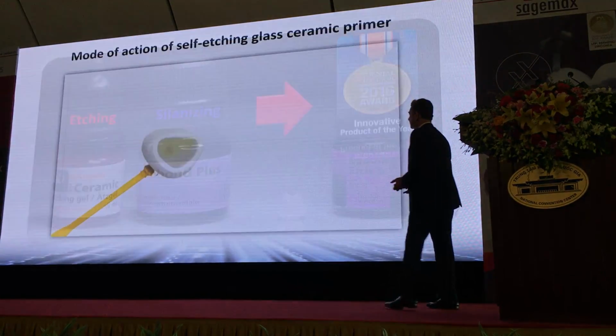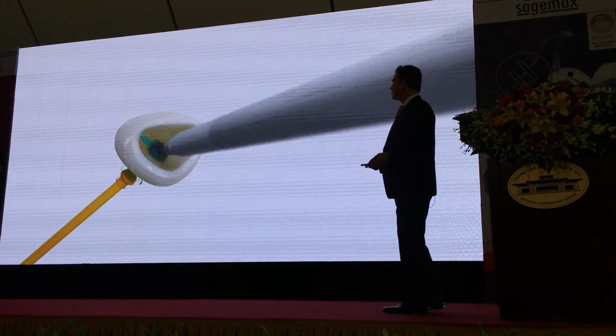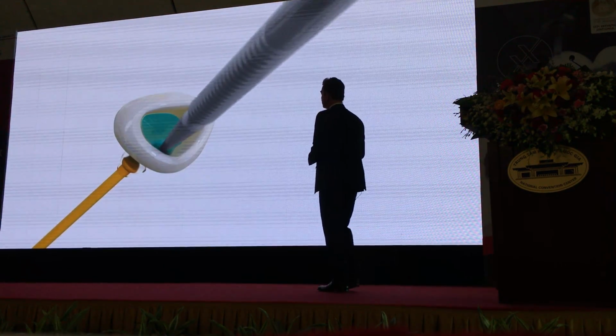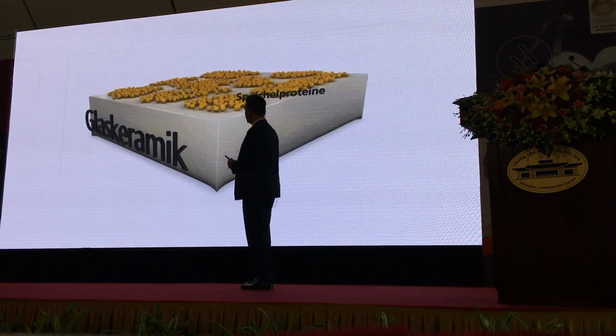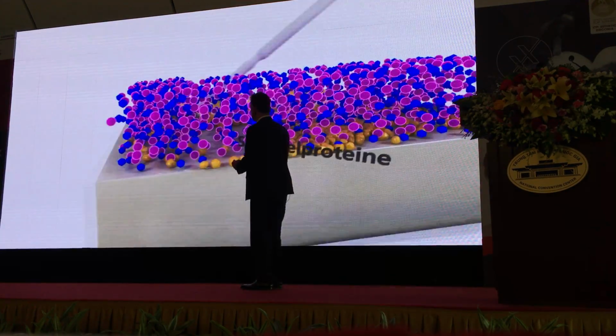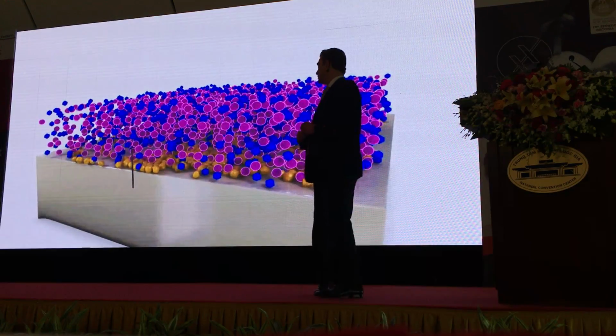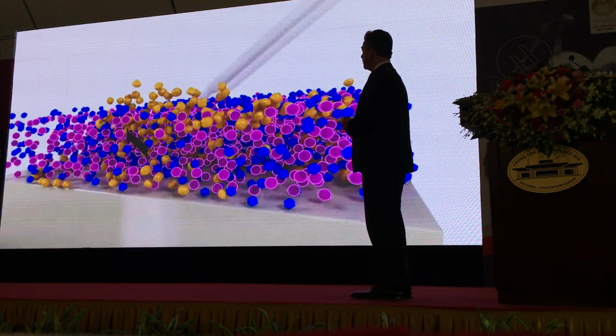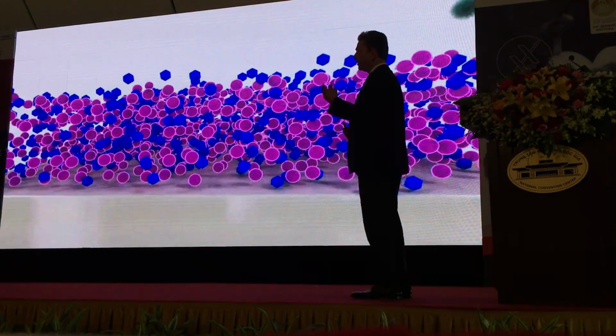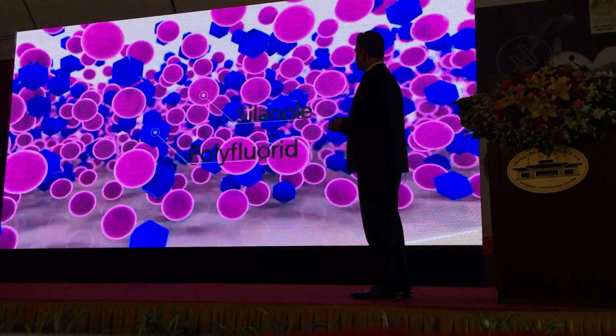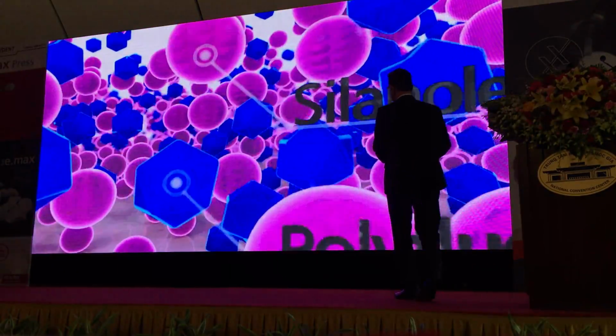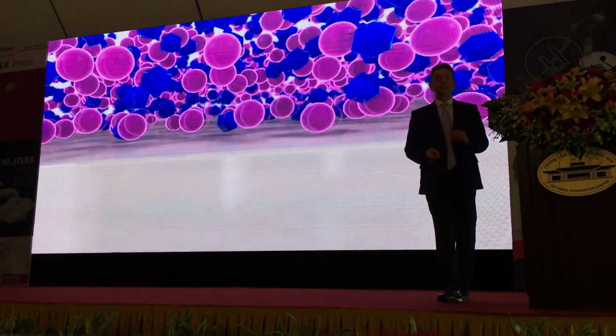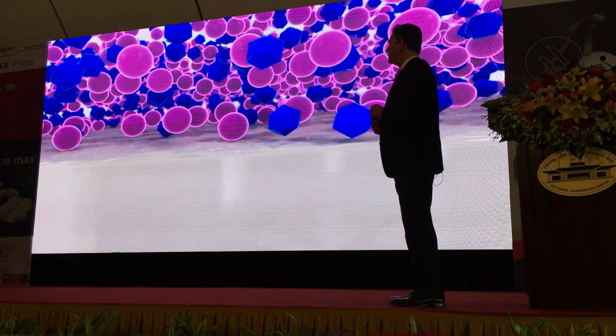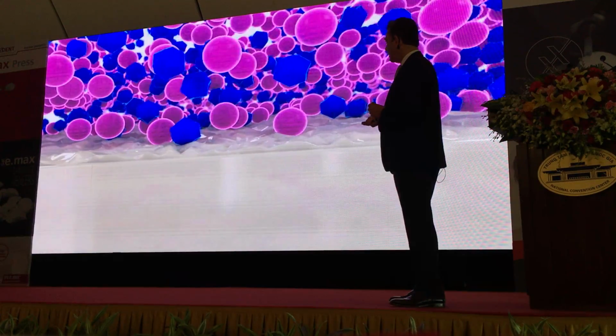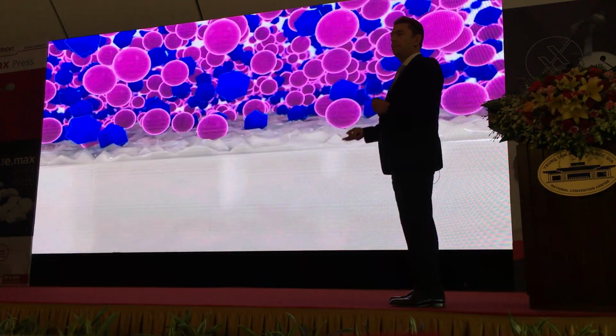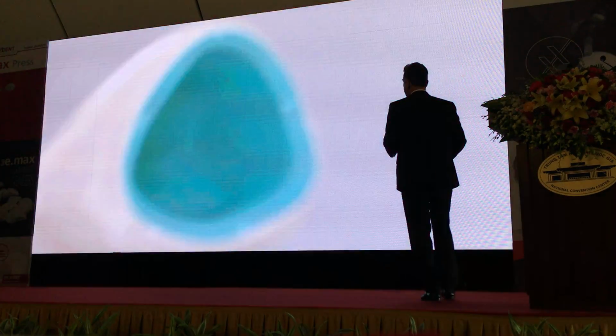Okay, so this is a very good idea. You just need to scrub it into the restoration. We scrub that in for 20 seconds, and then we are cleaning everything. So it's cleaning the whole thing. And now, of course, first of all, when we scrub it, we will get rid of all the contaminants on the surface. And we have a silane and we have a polyfluoride for etching. So the bluish particles is symbolizing the etchant, a polyfluoride, which is creating a rough surface on the ceramic. So it makes the surface rough.